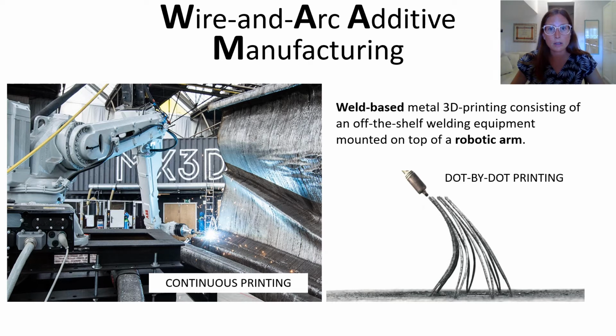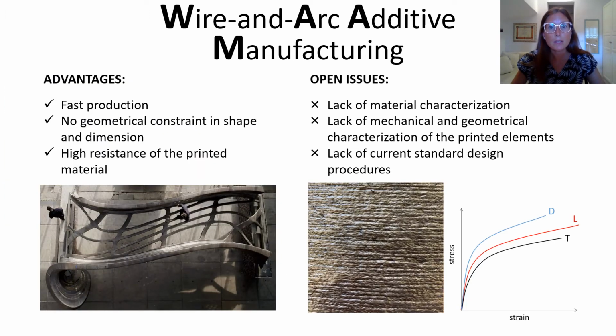Two of them are the so-called continuous printing, a layer-by-layer deposition to realize continuous shell-like elements, and the so-called dot-by-dot printing, in which drops of metal are printed one on the other to realize rods and lattice-like elements. The main advantages of this technology are the fast production of large parts with ideally no geometrical constraints in shape and size, and high structural resistance.